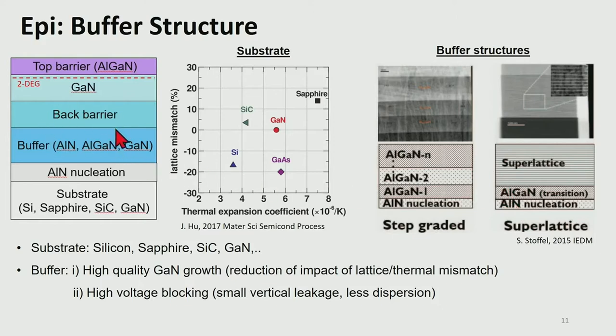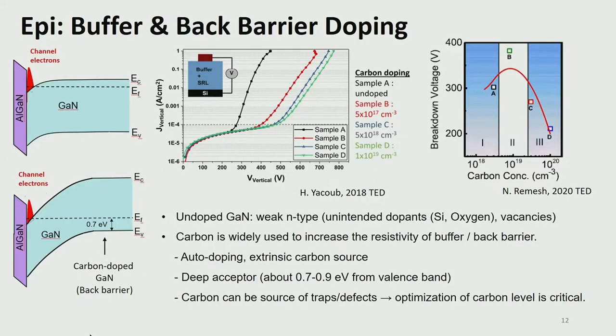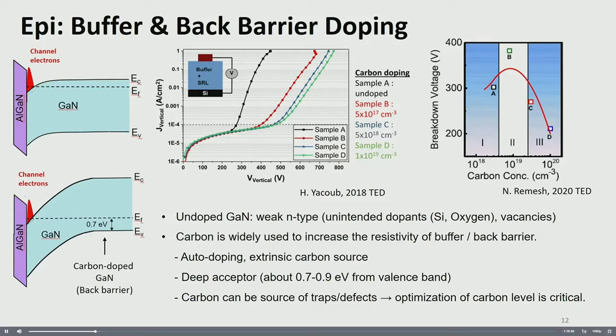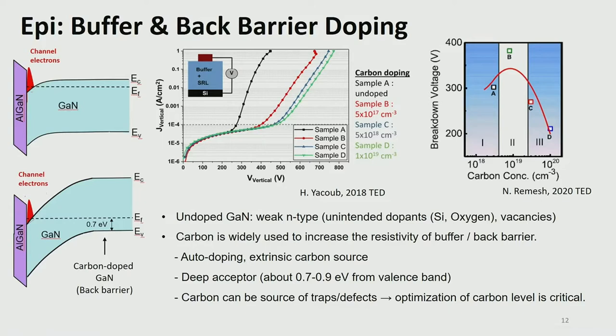The purpose of the back barrier is to suppress the vertical or lateral leakage current. If you grow the gallium nitride without any doping, the gallium nitride tends to become weak n-type. This is because the silicon or oxygen, which are present in the epi chamber, are good n-type dopants for gallium nitride. So if you grow just the undoped gallium nitride, the Fermi level is closer to the conduction band.